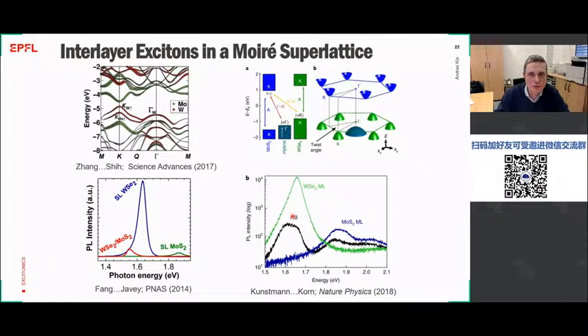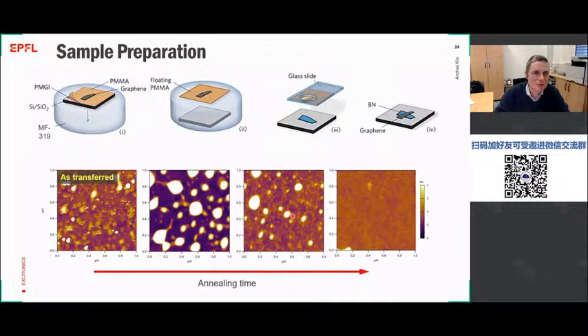And to get these excitons to show up, as I mentioned before, it's very important to create these high quality heterostructures. We use one of, and actually several different variations of, these transfer methods that have been very much popularized in the research community. We exfoliate one material on a substrate, and then using some kind of a sacrificial polymer, we can remove it and transfer and build a heterostructure on a target substrate.